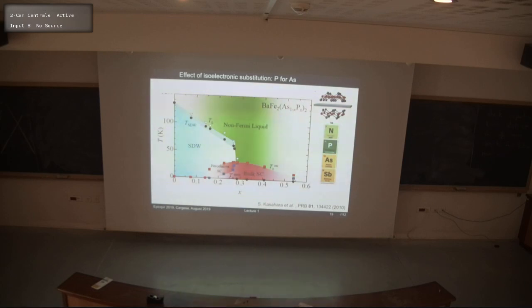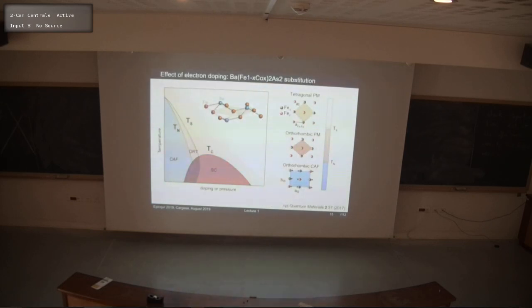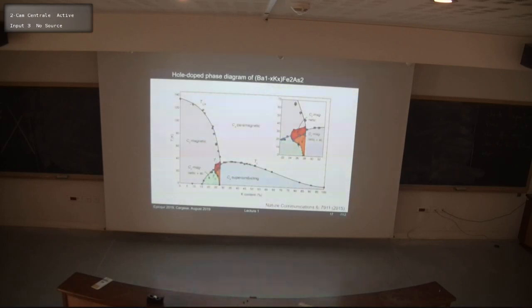Okay, so you're asking how universal all this doping is. There is universality in certain aspects, and I think especially this phase diagram compared with, well, let's say this phase diagram have very similar trend in behavior. Nickel and cobalt can be rescaled to really follow each other if you account for the same number of electrons being donated to the iron level. So I think if you can scale back how much you dope and how much your Fermi surface changes, you can scale the systems. However, if you also change anything structurally, then you won't be able to do that.